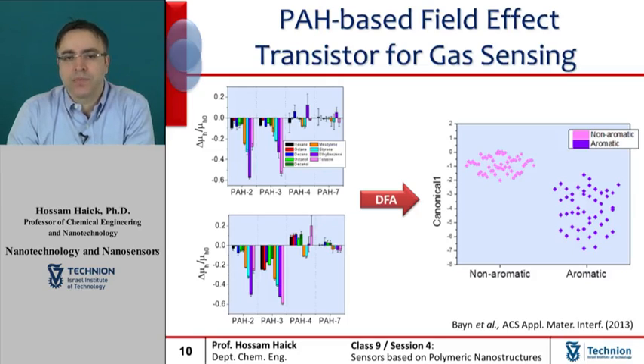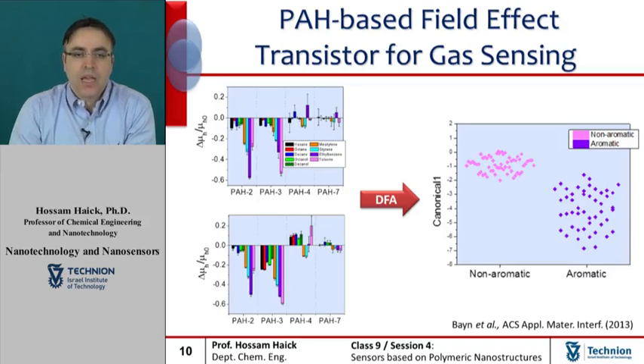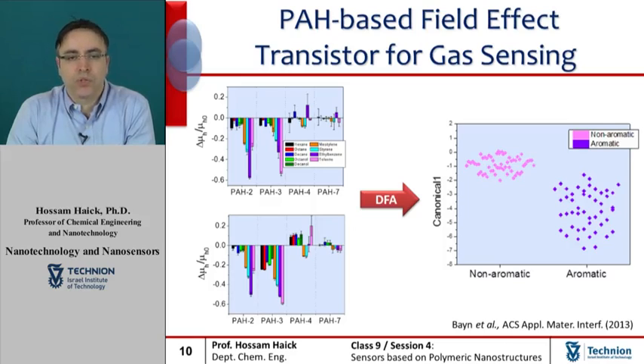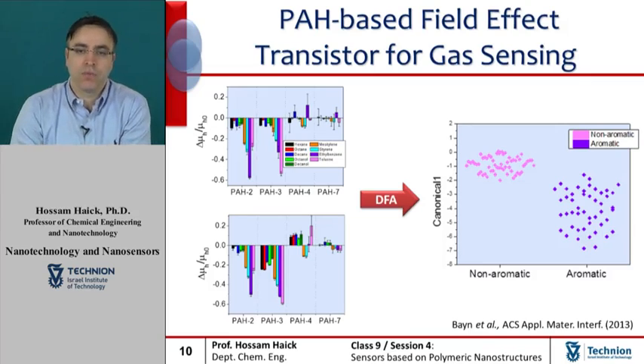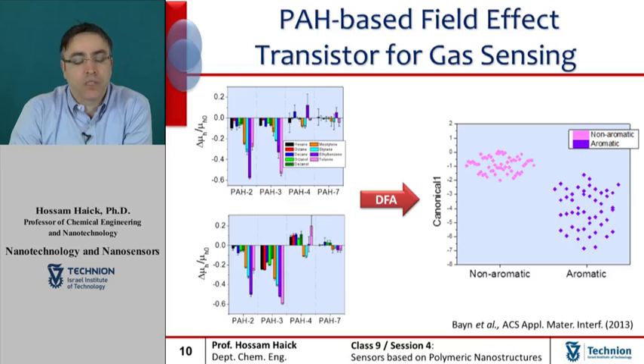In the right side figure on the screen, you can see discriminant factor analysis results separating the non-aromatic, namely octanol, decanol, hexane, octane, decane, and aromatic analytes, basically mesitylene, styrene, ethylbenzene, and toluene. The different dots stand for the response of the device upon exposure to different concentrations of the different VOCs, namely volatile organic compounds, in both 5% and 40% relative humidity. The accuracy level of discrimination in this case was 95%.